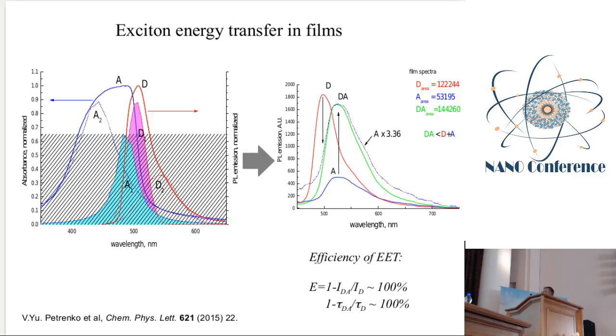So we can calculate the efficiency of the exciton energy transfer to be almost 100% in solid films of a mixture of donor and acceptor J aggregates. And this process also is very fast, less than 20 picoseconds, which was the limit of our measurement device. So we can conclude that in this case, the energy transfer proceeds by the Förster energy transfer mechanism.